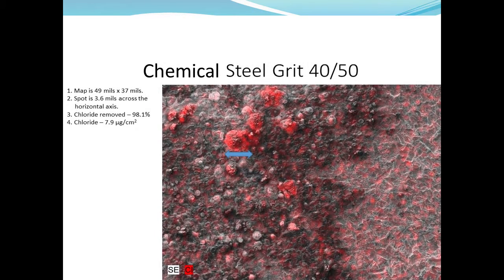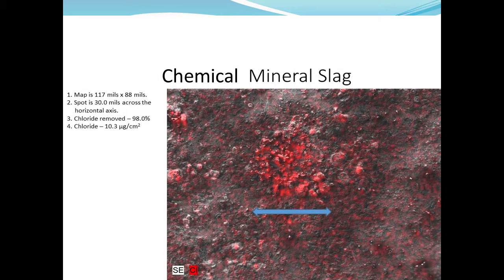We also observed in some of those clumping. As you can see here, we got relatively larger, maybe. Now, this is 3.6 mils, but most of them are grouped together. And in some cases, that's even more the case. Around the outside of this image, very little chloride, but in the middle, a bunch of very small deposits of chlorides.